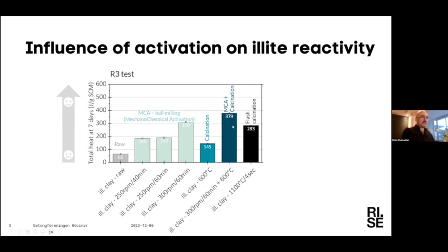it's working. Here, for comparison, I also put the result of the kaolinitic calcined clays. What we can see from all this data is that we can actually have quite good results with illitic clays, even comparable to what we have with kaolinitic clays.